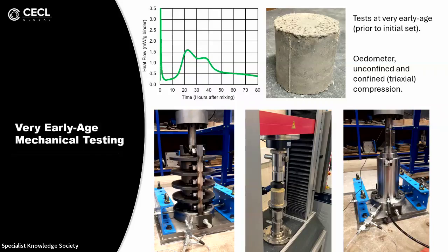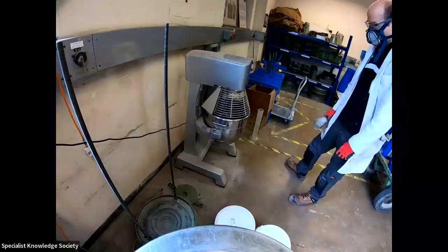So we've been doing our very early age tests at less than 2 hours typically from mixing. So this is well before this initial set and the main chemical process kicks in. And that 2 hours is basically as fast as we can strip and demold the sample from the equipment and set up the strength test. So the results at this very early age are really mechanically derived strength and stiffness purely from that compactive effort.